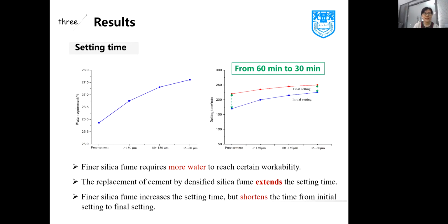We studied the setting time. From the figures, you can see finer silica fume requires more water to reach certain workability. The replacement of cement by densified silica fume extended the setting time. Finer silica fume increases the setting time, but it shortens the time from initial setting to final setting. You can see from 60 minutes to 30 minutes.